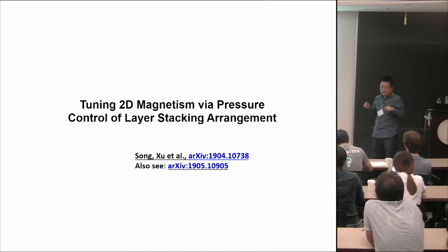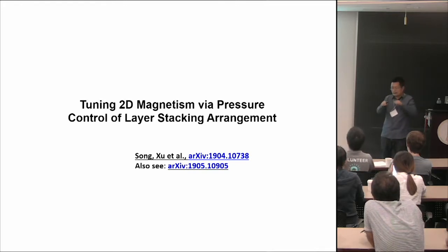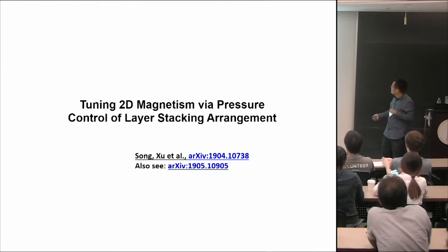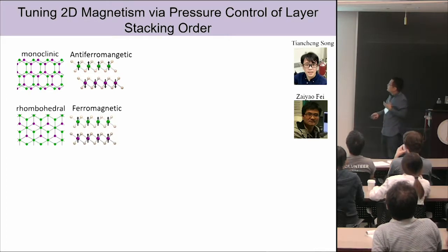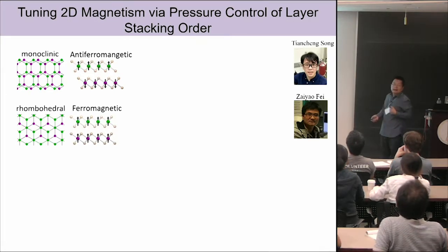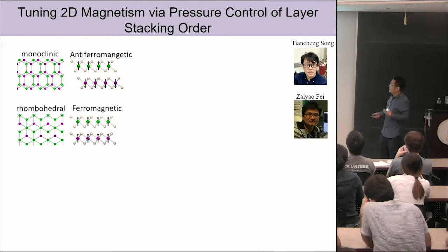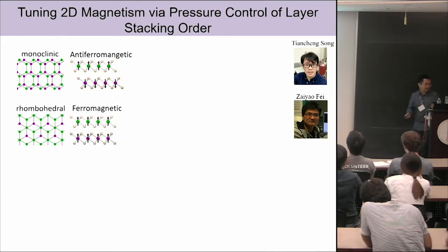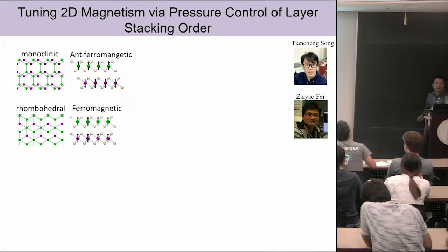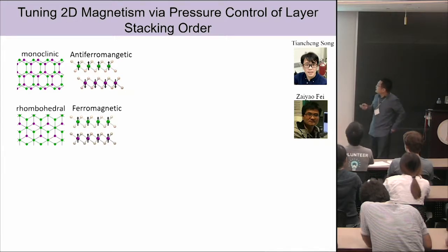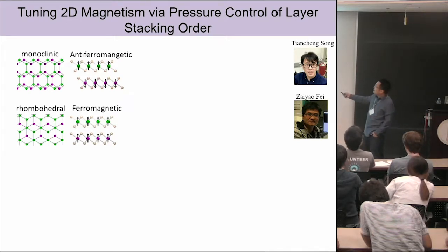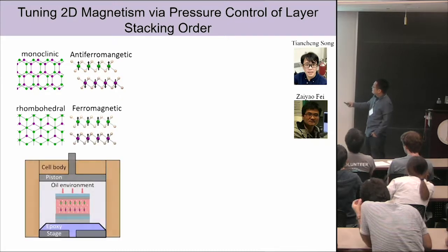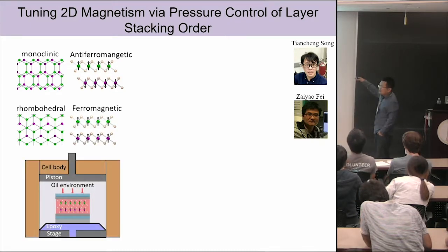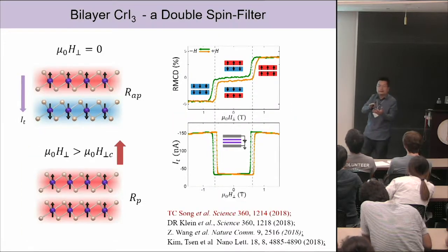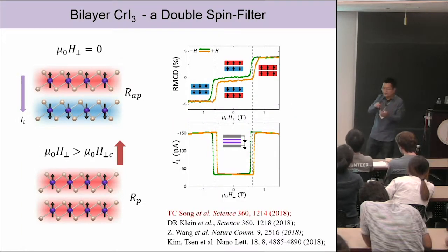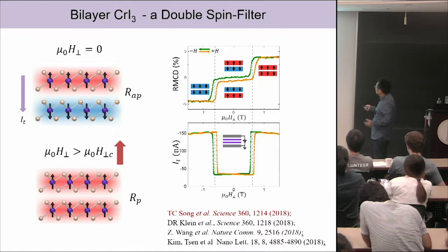And last, I want to show you examples of how we can control this layer stacking and these magnetic orders. So let's go back to chromium triiodide, and I remind you of the simple results we have. Let's see how much time I have. Maybe another 10 minutes, right? Yeah, that's perfect. So for this, remember, monoclinic is antiferromagnetic, and rhombohedral is ferromagnetic. Then we try to apply hydrostatic pressure to control the interlayer couplings. So here's an example, right?